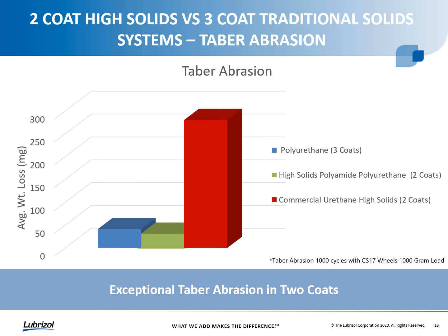because you're retaining more of that film as you're abrading the surface. And what we see sometimes is that materials that have very good hardness or high coning values correspondingly tend to have poor abrasion resistance, that when you abrade the surface, more of it wears away. So you'll have a high coning, but you'll also have a high Taber number. And with the polyamide technology, we find that you can have very good hardness values, but correspondingly have very low Taber numbers, so good abrasion resistance as well.